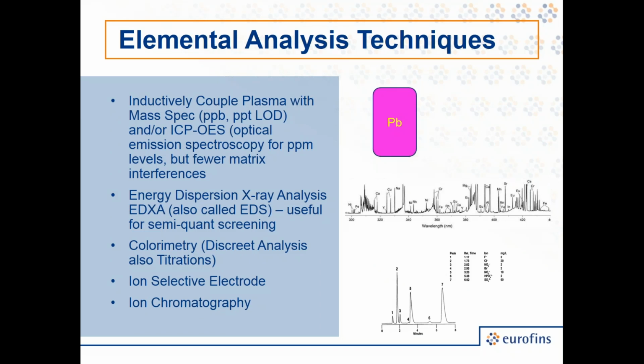When we talk about elemental analysis, this is going to be for most of the things that are kind of on the lower or left side of the periodic table. So, of course, most people are common with all the heavy metals. But we use inductively coupled plasma, and we can do that with either optical emission spectroscopy or mass spec. Optical emission is a little better. It has fewer matrix interferences. With mass spec, it's possible to get down to parts per billion, in some cases part per trillion limits of detection, which is very, very important, especially for excipients or when you start to talk about pharmaceutical type of applications.